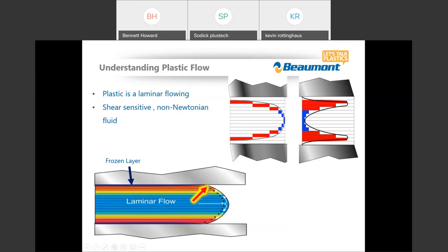Meanwhile, the laminates in the center are not rubbing up against that frozen layer, so they're a much cooler, more viscous material during fill. I just want to specify that we're talking about the injection time. It is understood that during cooling, our laminates in the center are the last to cool because they're the furthest away from our cold steel wall. During fill, the higher shear rate, hotter plastics are against that frozen layer. So if you take a different cross-sectional view, during fill you have this annular ring of higher shearing, less viscous, much hotter plastics around the perimeter.